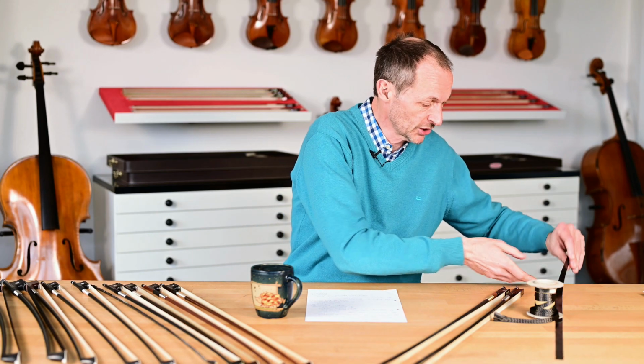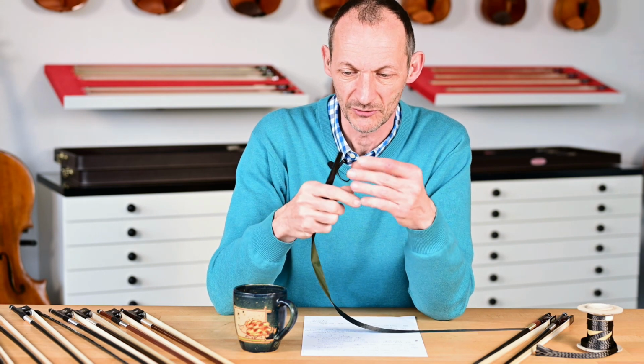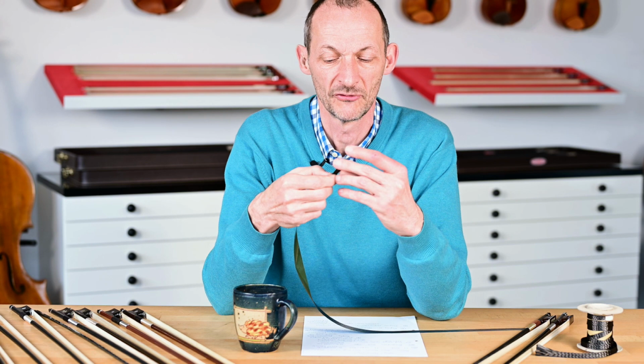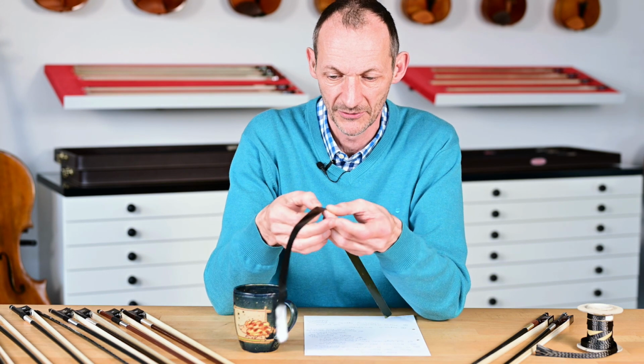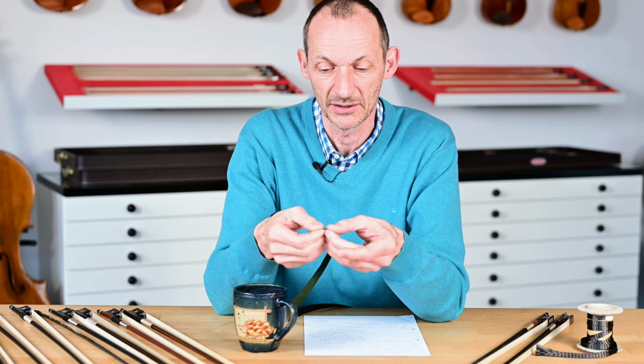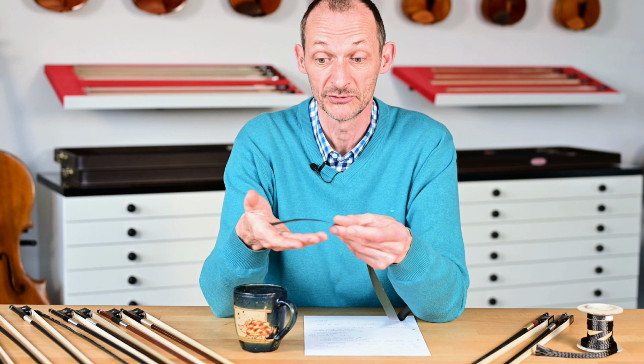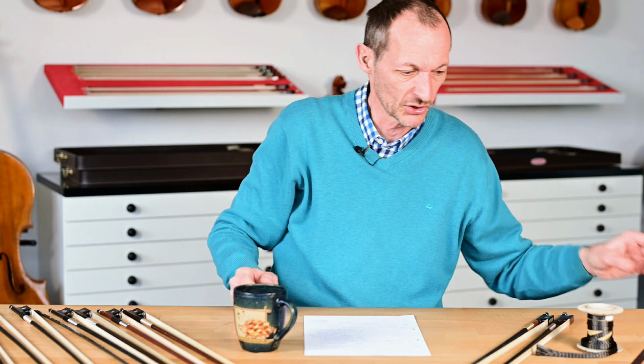Okay, first let's look at this flimsy stuff that we use to make our Arcus bows. You know, this is called a prepreg. This is ultra thin stuff. This is actually including a foil. You know, the carbon fiber is even less than half that. Very delicate stuff. That's what's so difficult to work with. And it has the resin already included, very evenly spread out, which is one reason why we can make these bows so thin and so light. But terrible to handle.